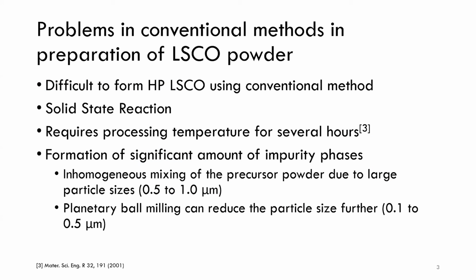However, it is difficult to form high-purity LSCO powder using conventional methods. The most common method of producing LSCO powder is the conventional solid-state reaction method. In the solid-state reaction method, constituent metal oxides and carbonates are mixed and annealed at very high temperatures for several hours. In addition, the problem with the solid-state reaction method is often the formation of a significant amount of impurity phases.